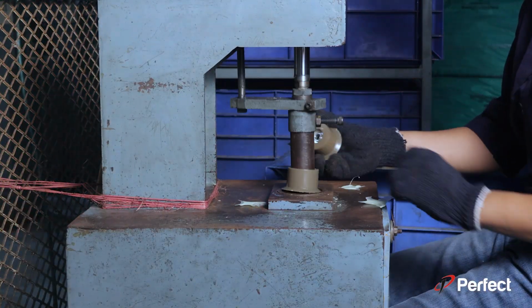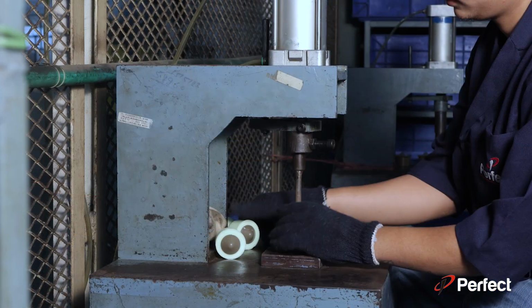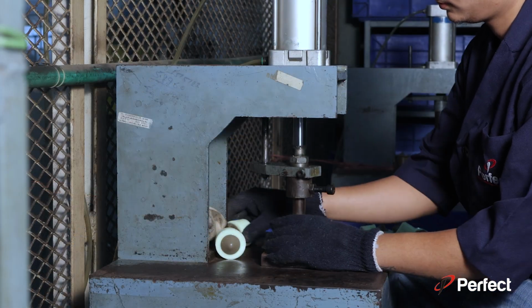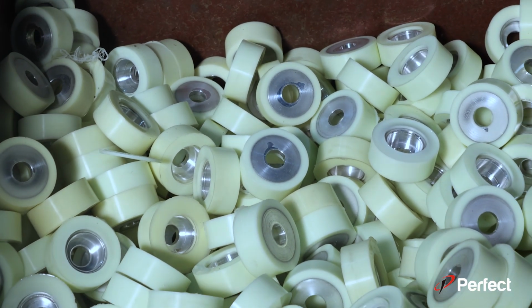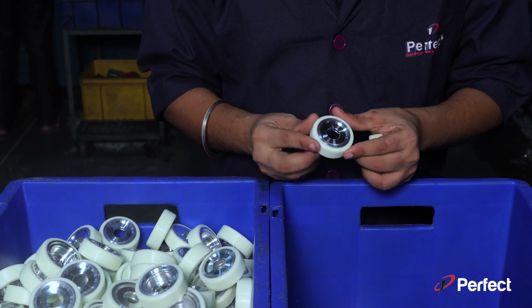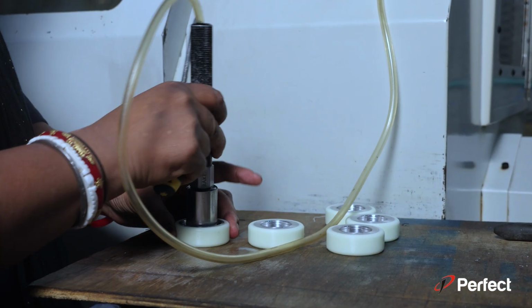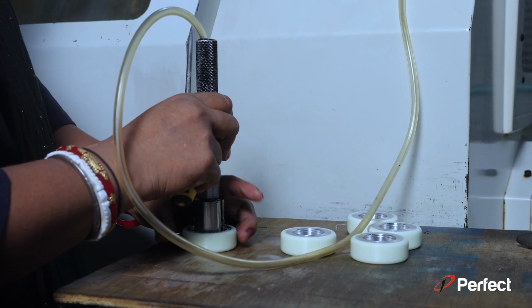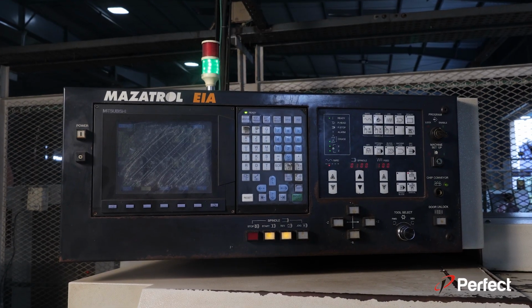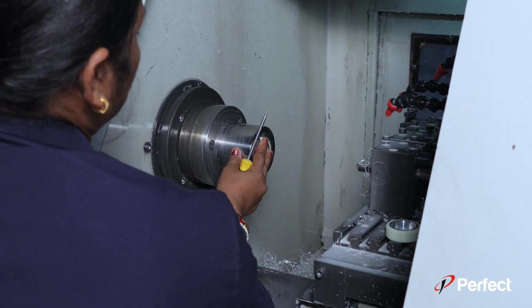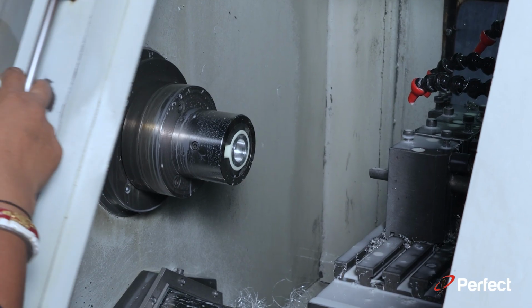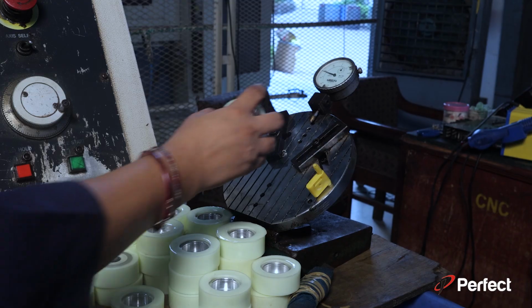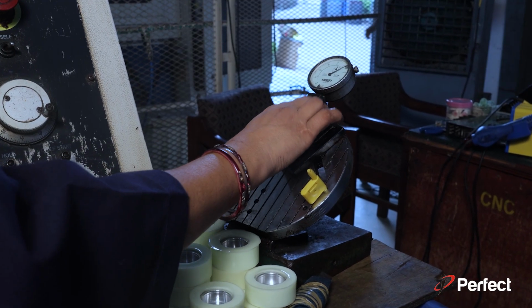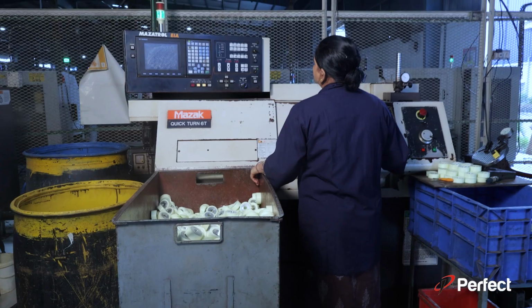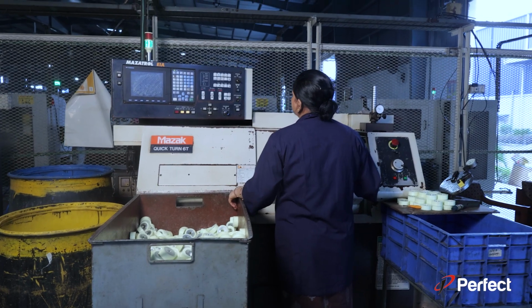The polypropylene cup molds are then broken in a demolding machine to extract PU rollers, which are immediately inspected for any faults. Following these steps, the PU rollers are remachined to ensure utmost precision, up to 8 to 10 microns, on both inner and outer diameters. Dimensional accuracy and quality are maintained through pneumatic gauges installed on every CNC machine.